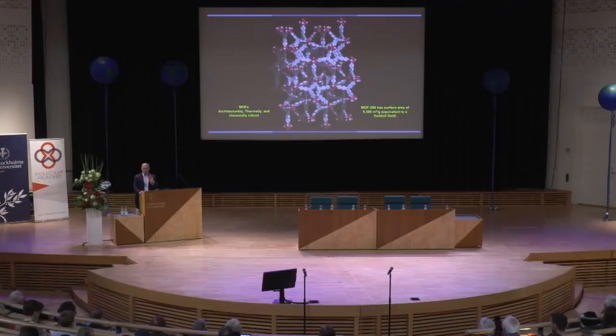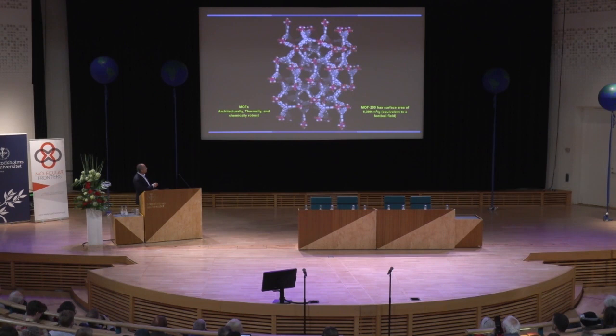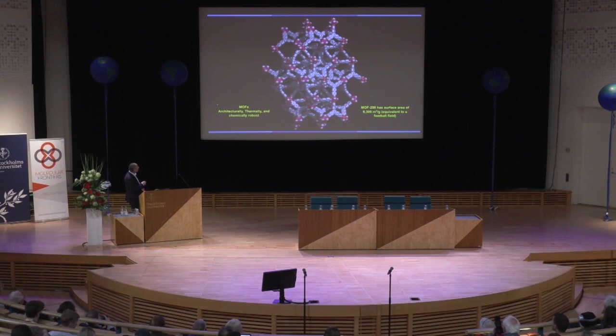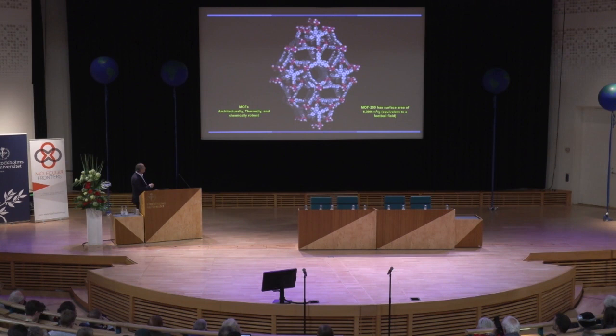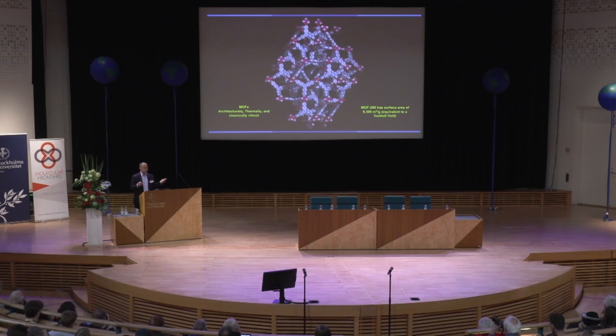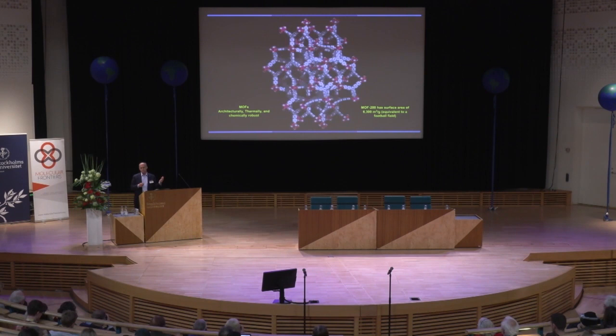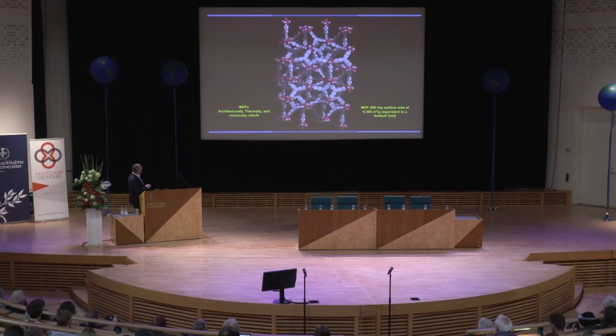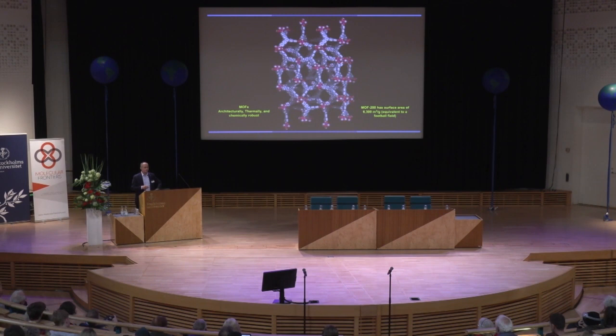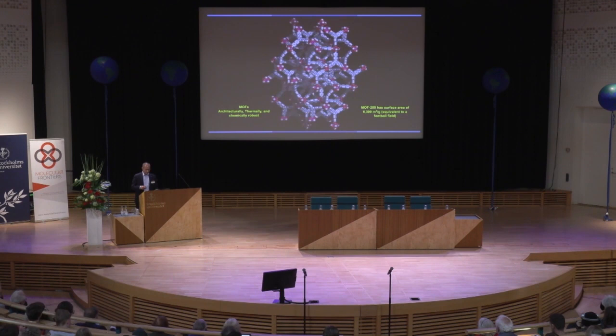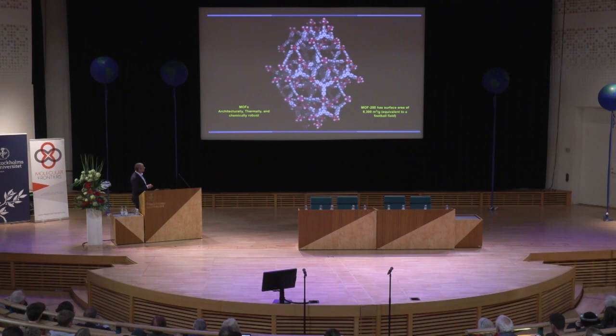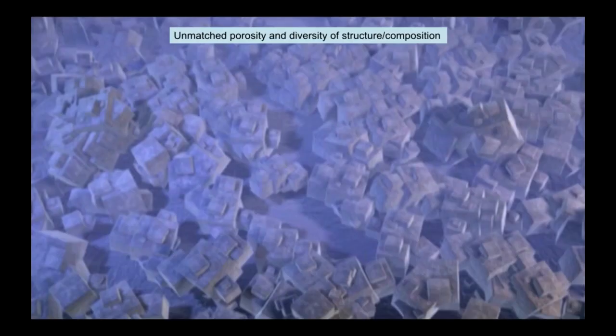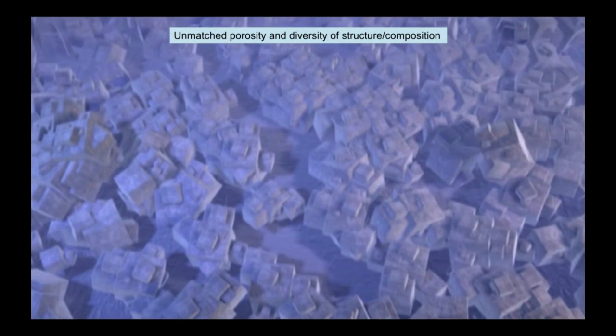MOFs are architecturally robust because these secondary building units anchor the structure. They are thermally stable because they're made from very strong bonds — carbon-carbon bonds, carbon-oxygen bonds, and metal-oxide-type bonds — all at least 300 kJ/mol. Many MOFs can now be made as chemically robust: stable in water, in acid, in base, and under refluxing conditions of organic solvents and water. We have created a whole new world of extended structures made as crystals because we have overcome the crystallization challenge.